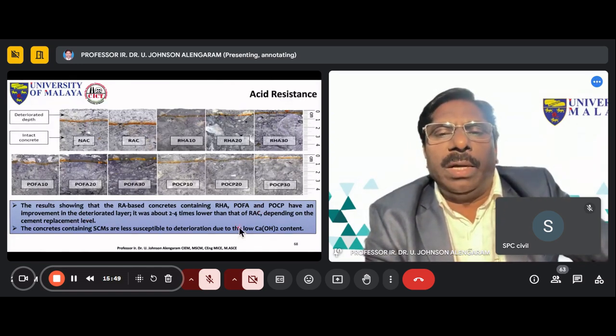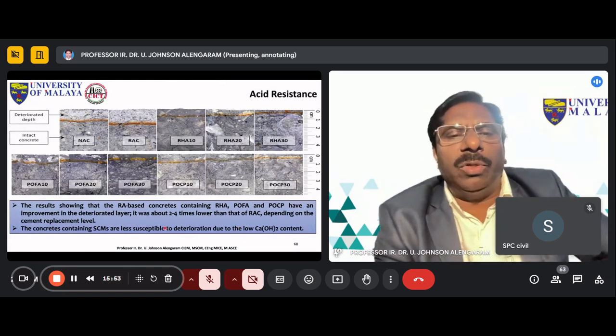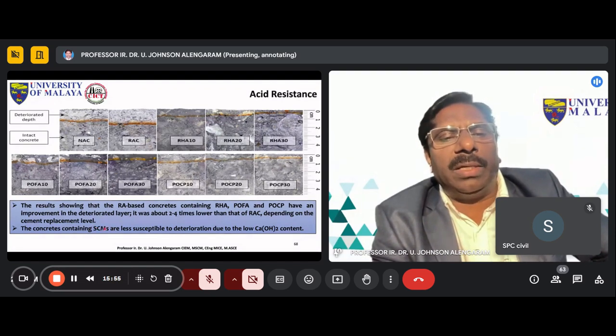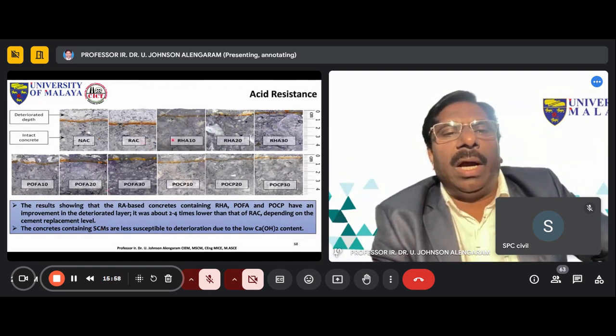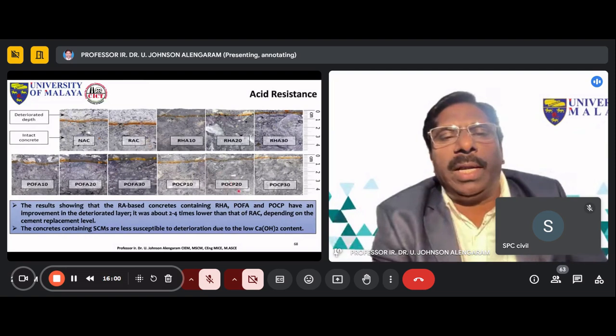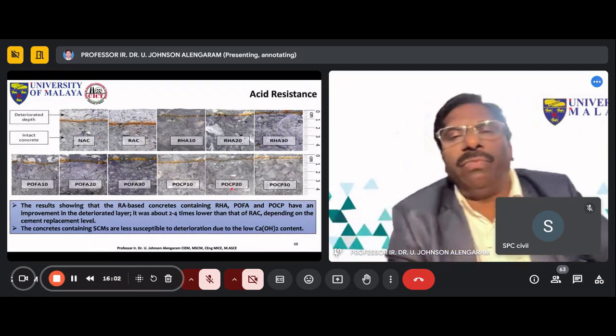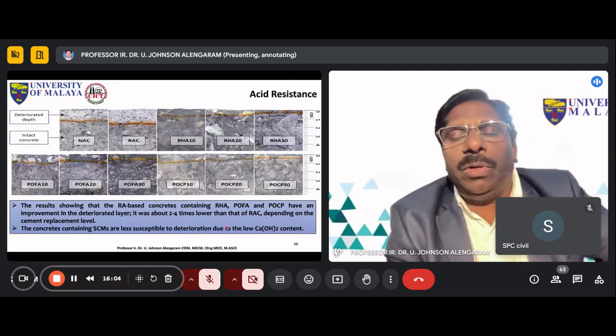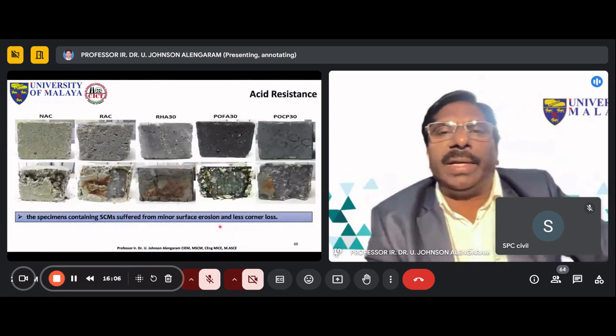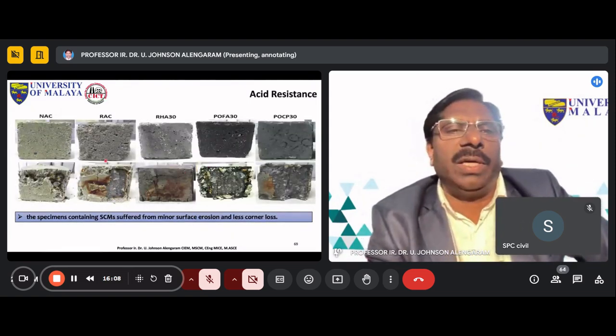So this is very important because, as I said, this calcium hydroxide has been consumed due to the supplementary cementitious material, that is the rice husk ash or palm oil fuel ash or palm oil clinker powder. They do react with the calcium hydroxide to produce more calcium silicate hydrate. So you see the deterioration of the surface.